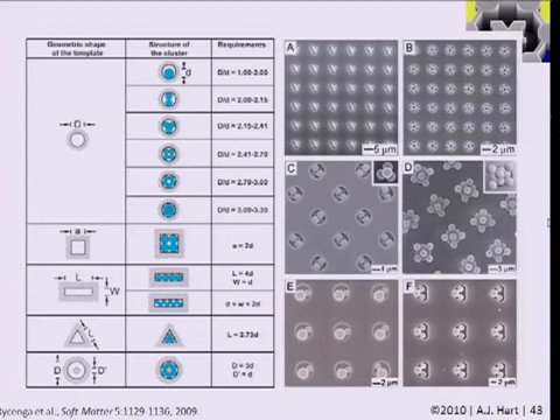And then if you expand the hole a bit larger, such that its diameter is between 2 and 2.15 times the diameter of the sphere, then you get preferentially 2 particles in it that are packed in a kind of lateral stack like so. And then if you go slightly bigger, then you get 3 particles, slightly bigger and 4 particles, and 5 and 6 and so on. And you can also get more interesting multi-layer structures by the tendency of particles to pack at interstitial sites on previously assembled layers.